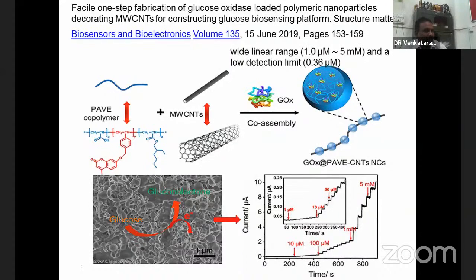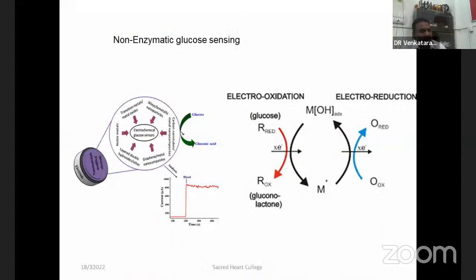So for that purpose also, we try to eliminate glucose oxidase by developing non-enzymatic sensors, where we directly monitor glucose oxidation at a metal, because carbon materials will not undergo oxidation because of the requirement of a higher potential than your metal surface. So we try to use platinum and gold, especially these two materials, along with other transition metals like cobalt and nickel. All conducting materials can be used for monitoring the glucose reaction directly without using any enzyme. Here, the sensor metal surface generates an oxide hydroxide group, which interacts with the glucose, and it forms gluconolactone, gluconic acid or hydrogen peroxide as products.